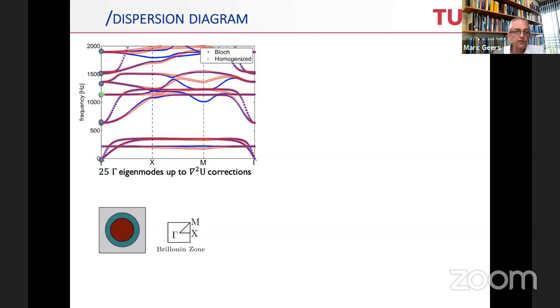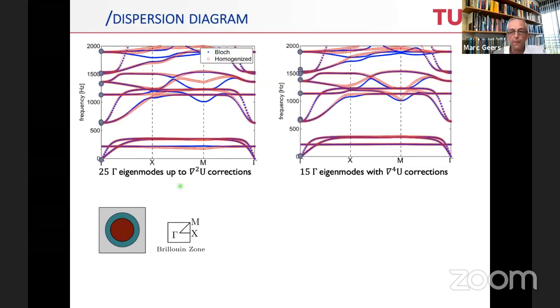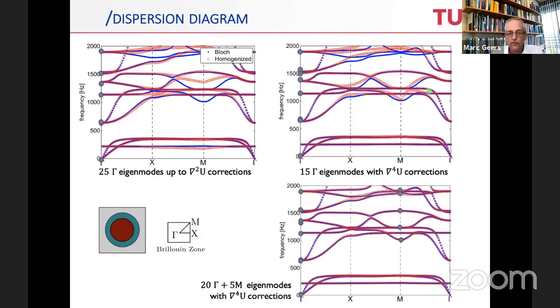So I've been biased. I took all my modes here on the left, and then you see that I get deviations on the right. If I reduce the number to 15 and I increase the order of my corrections, I have somewhat improvements, but not fantastic, I would say. Whereas if I would split the 25 into 20 in the gamma points and 5 in the endpoints of the Brillouin zone, then clearly, since I've taken out a few modes here, I have a lot better approximation of the true dispersion spectrum than I had originally.